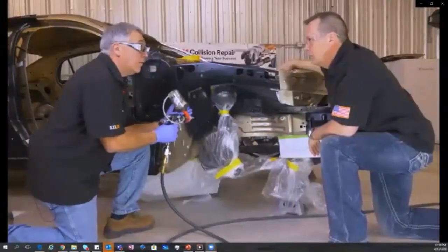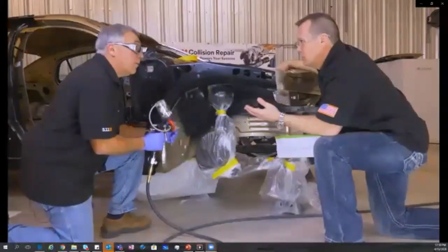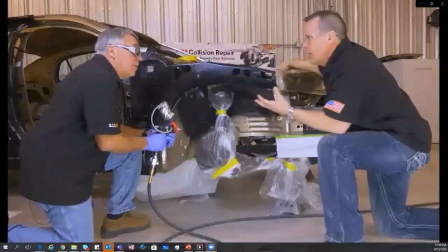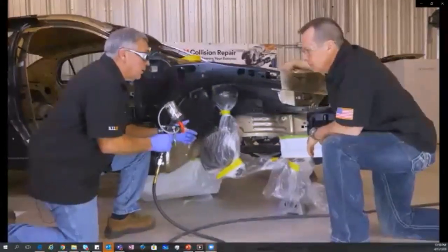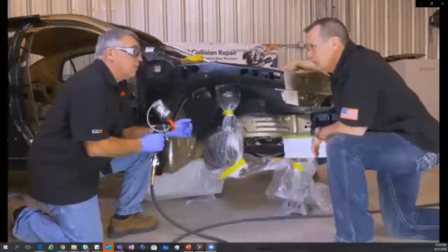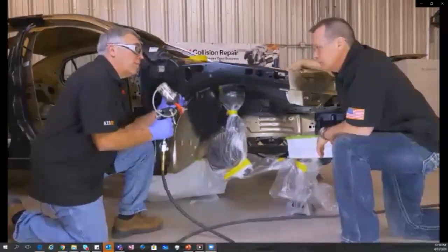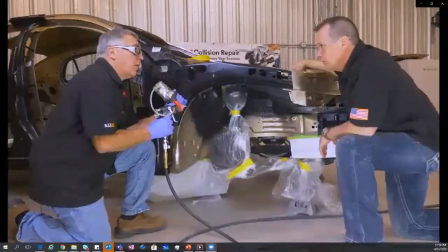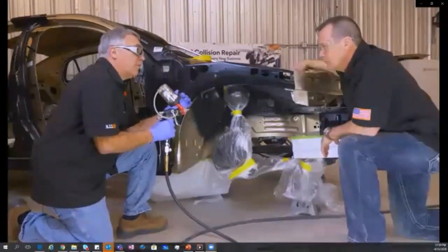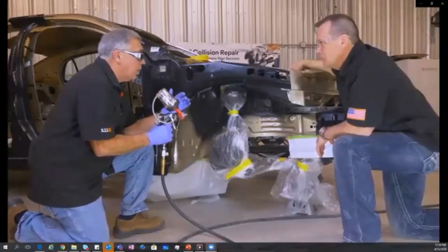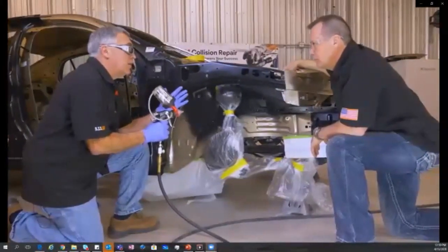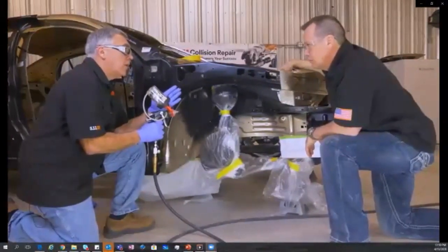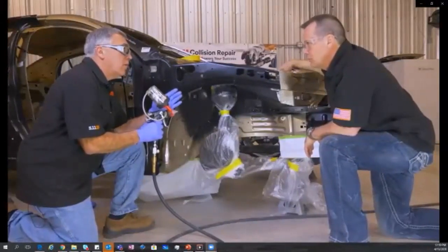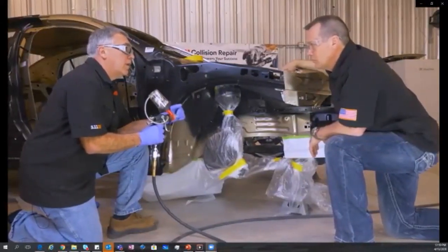It's going to resist the stone chips. What do the additional coats do for you? Why so many coats? That's a great question. I've seen lots and lots of salt spray tests where we looked at kind of a breaking point for where things were going to be able to prevent corrosion after 1,500 hours. And it always seemed like a dry mil thickness around 10 or slightly above 10 mils was going to give you the protection you really needed under really harsh conditions.